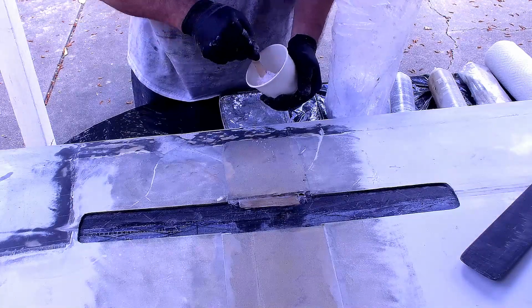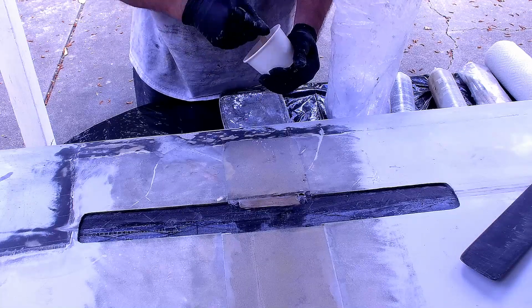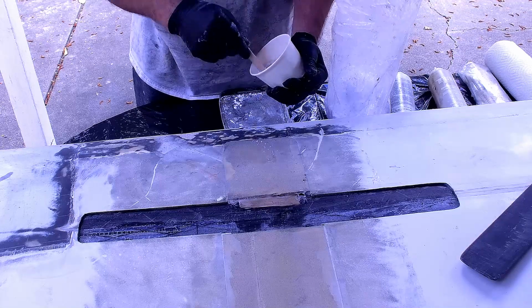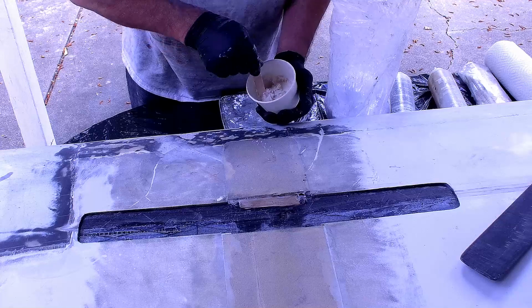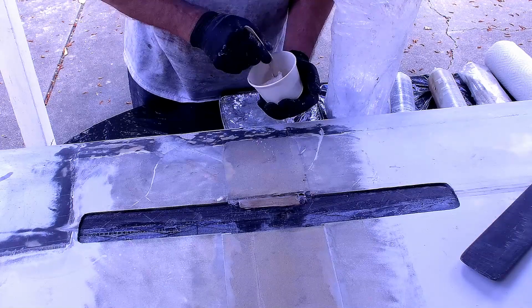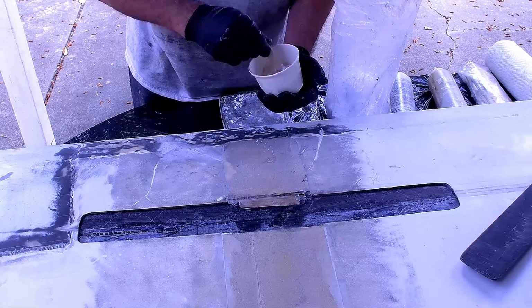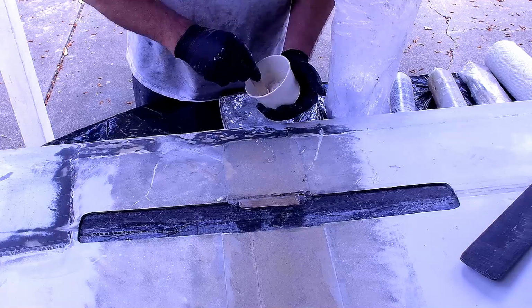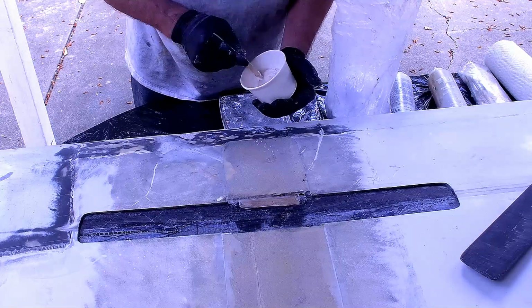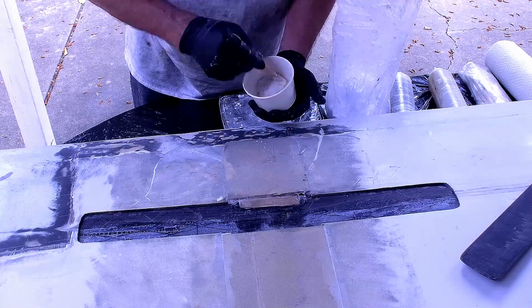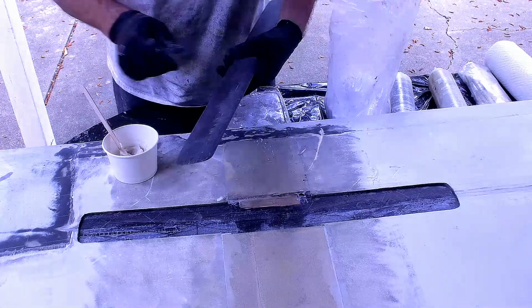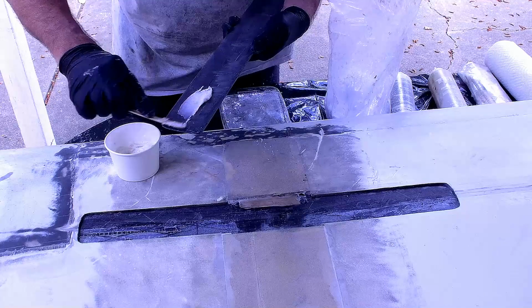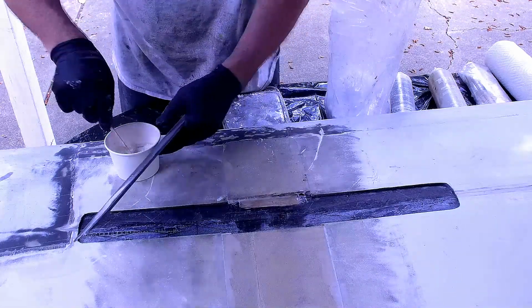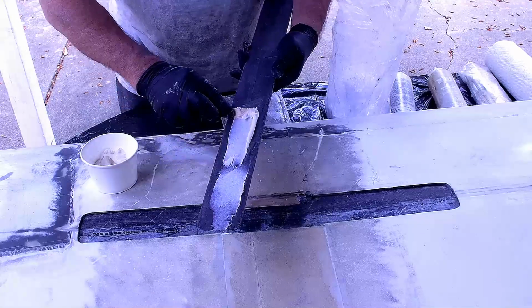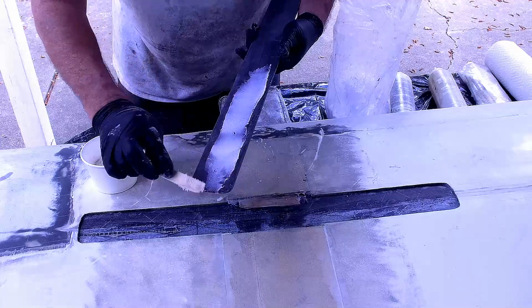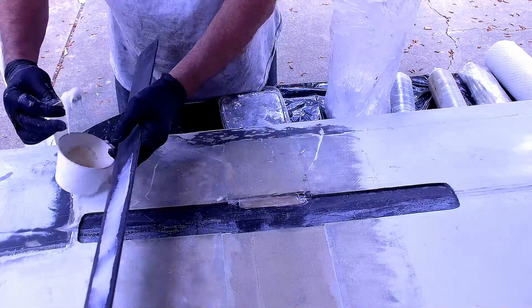that's 24 square inches. And the adhesive that I'm using is good for 2,000 pounds per square inch. So 24, let's see, 24 square inches times 2,000. There's 48,000 pounds of shear strength on each side. Now the maximum load in the spar is about 30,000 pounds. So 48,000 pounds per side. This doubler is not going to pull loose from the spar. The doubler itself, being pultruded, it's 1/8 of an inch thick, 2 inches wide, and that material is good to 320,000 pounds per square inch. So this doubler is phenomenally strong and stiff, way stronger than it ever needs to be for this aircraft. It's a little bit heavy, but this was the simplest way to repair it, was to put a doubler across the full width of the spar.